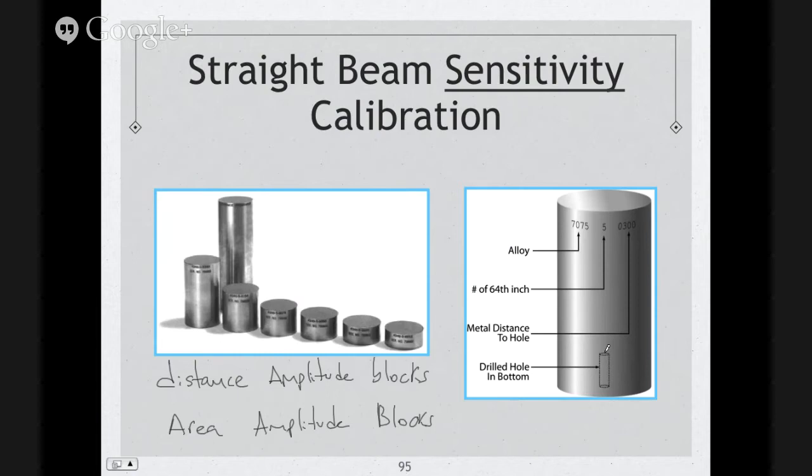And it's flat. So what you do is you put your transducer here on top of this, and you want to be able to get this reflector. The sound coming back from this hole, but also the sound that's around it coming to the back of it, going back into the transducer. Okay? So you're going to see something like an initial pulse. You're going to see the sound coming out of here, and then the sound around it, you're going to see another echo, and another spike.